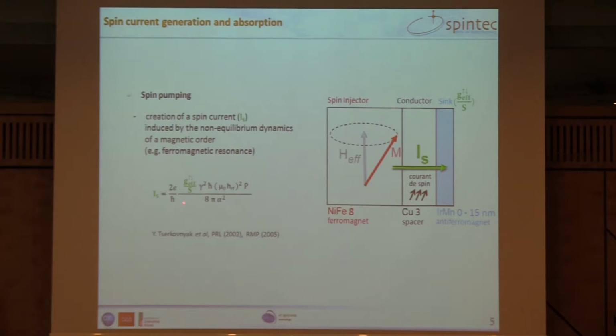That creates a spin current, and this spin current is directly proportional to this effective spin mixing conductance that contains all the physics of the absorption by the interfaces and within our antiferromagnet. So experimentally, we want to measure or to have access to this effective spin mixing conductance.